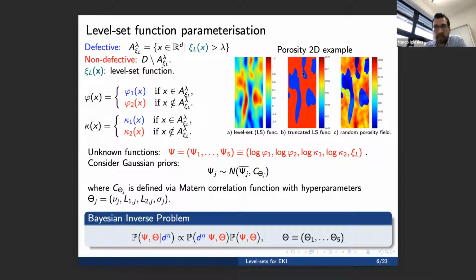So that allows me straight away to produce some random sample of a porosity in this case that will have a defect when the level set is above the threshold lambda and the background value if it's less than that. And then obviously, to be realistic, we can add some variability within the defect and outside the defect by introducing additional random fields. So to summarize, this porosity field that you see here in the right panel comes from truncating this level set function, and by adding a function phi1 in the defective region and a function phi2 in the non-defective region, which you can see here.